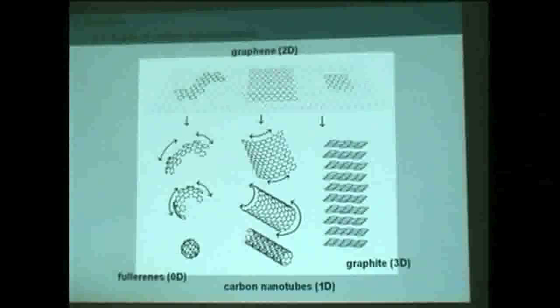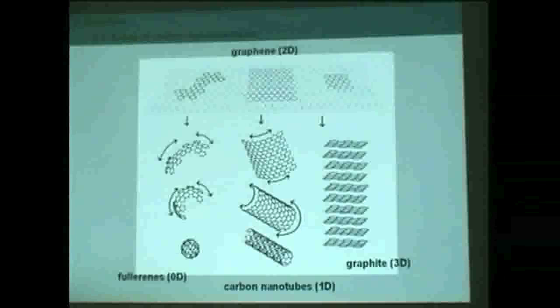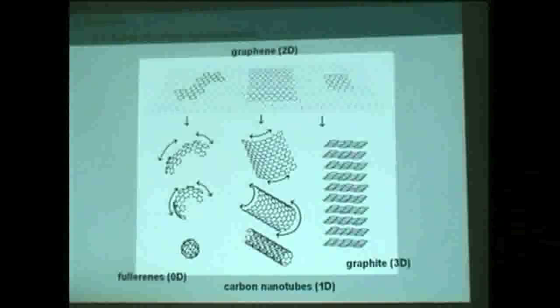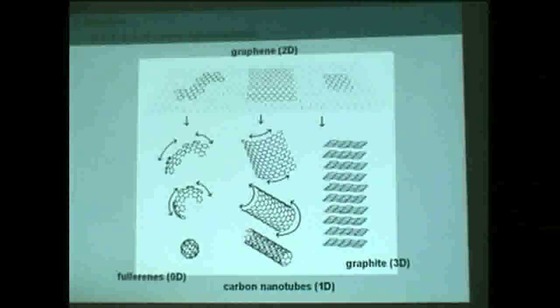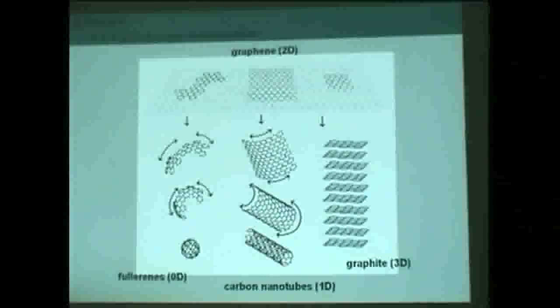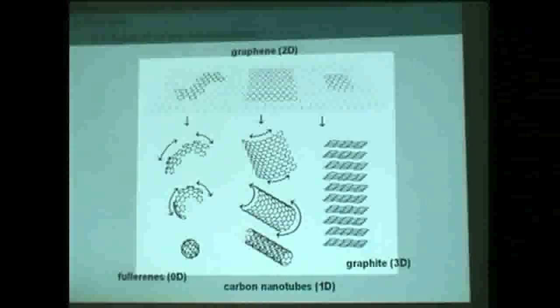Now, if we start from graphene, we can do many things. For instance, I already presented graphite. If I take several planes of graphene and stack them together in some particular stacking configuration, I will make graphite. As you see, graphite is a three-dimensional crystal. Now, I may take only one plane of graphene and roll it. If I roll this plane of graphene and close it, I can make a tube, a tubular shape. These are the families of carbon nanotubes, and this is only a tube, a cylinder, so it's a one-dimensional structure. And if we repeat this unit several times, if we create a translational symmetry in only one direction, then we will create a one-dimensional crystal, because there is translational symmetry in one direction.